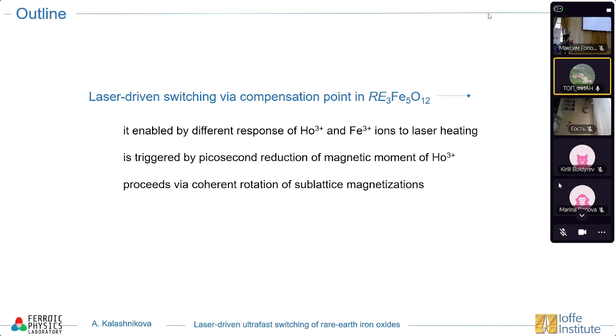I wanted to ask if you tried to calculate the heating, the laser heating. Yes, sure. For the first part, basically for experiments with metals and for experiments with orthoferrites, it was done. And heating depends, of course, on the fluence. In metals, it's usually up to 100 to 200 Kelvin. In rare earth orthoferrites, of course, depending on absorption, it will be several Kelvin or several tenths of Kelvin.